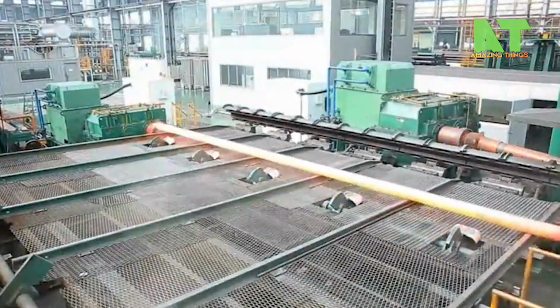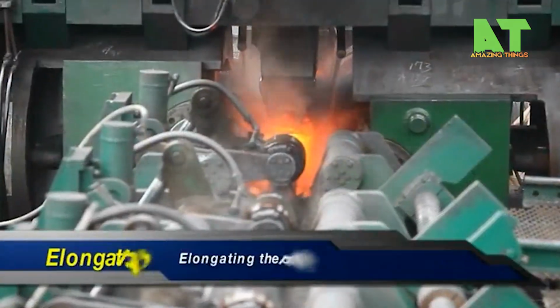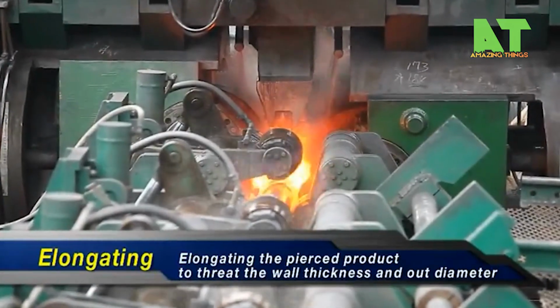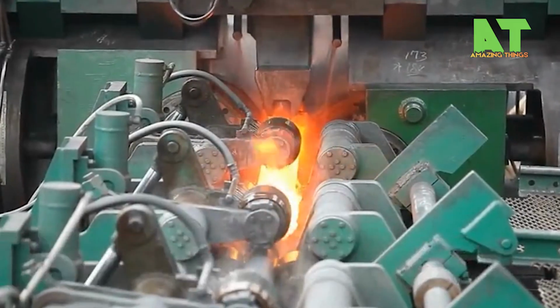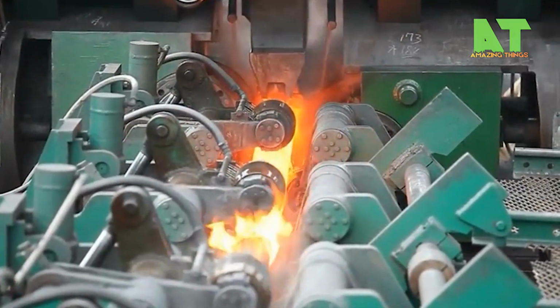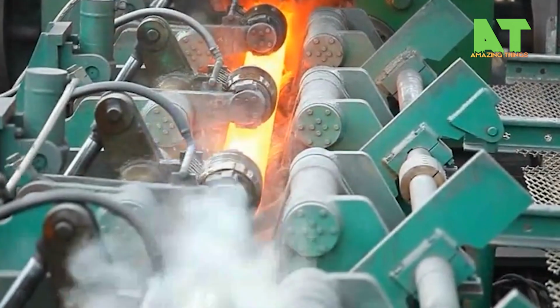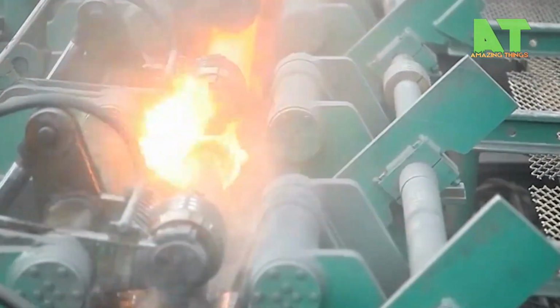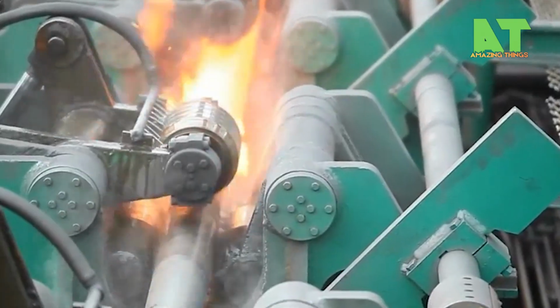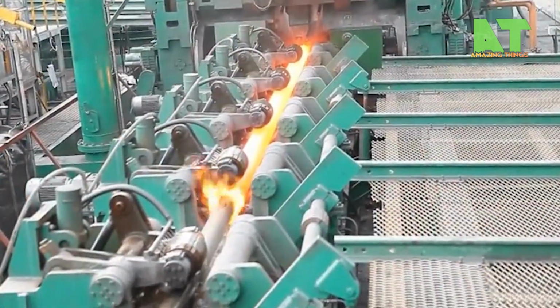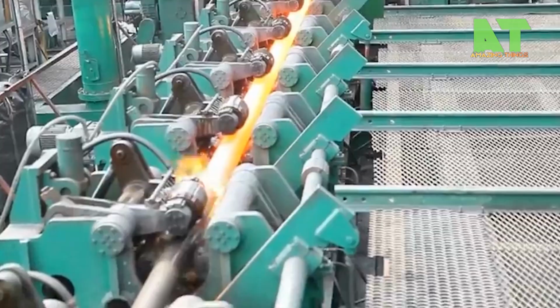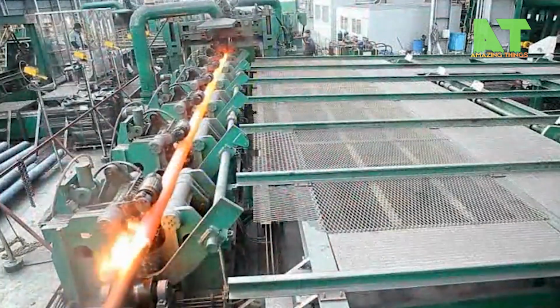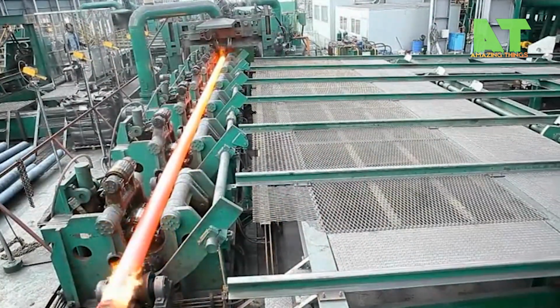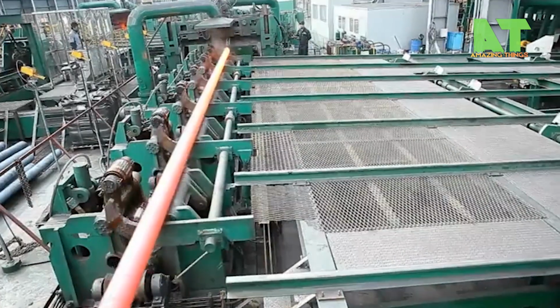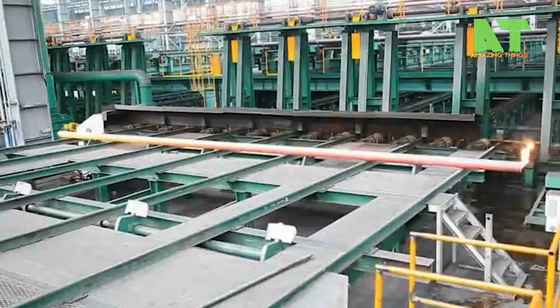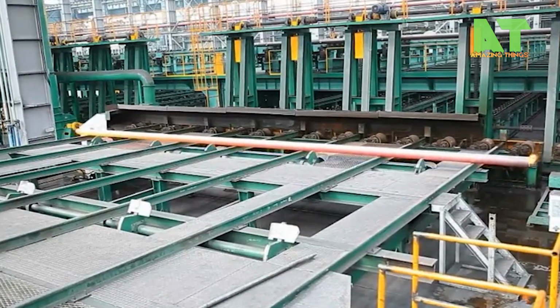These billets are first inspected and then loaded into a rotary hearth furnace, where they're brought up to temperatures of around 1250 to 1300 degrees Celsius. At that heat, the steel glows a brilliant orange-white and becomes workable enough for what comes next. This is where the magic happens, the Mannesmann piercing process. The red-hot billet is fed into a piercing mill, where two barrel-shaped rolls are set at opposing angles to the billet's axis. As they rotate, they don't just spin the billet, they create a powerful helical rolling action that causes immense internal stress inside the steel.